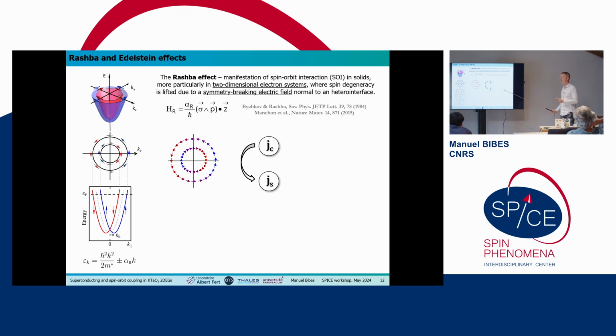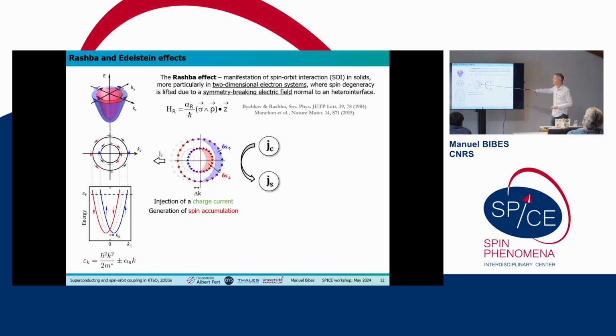That's the Rashba effect. A consequence of the Rashba effect, which was discovered by another Russian theoretician, Edelstein, is what happens when you apply a charge current to a Rashba system. If you apply a charge current to this system, you shift slightly these contours. And because of the spin-momentum locking, you generate an excess of spin density here and there with opposite spin directions, but there's much more blue spin than red spin. So at the end of the day, you generate a finite spin density. Even in a non-magnetic system, if it has this Rashba splitting, you apply a current and you generate a transverse magnetization. And this magnetization can diffuse as a spin current. This is how you can do the conversion from a charge current to a spin current. So this is another way to do that, different from the spin Hall effect that Javier mentioned this morning.